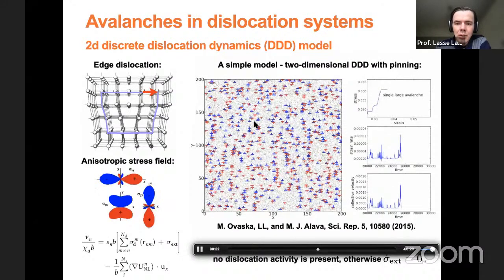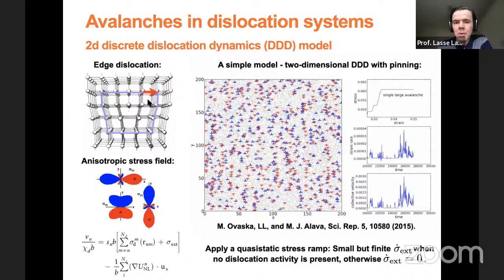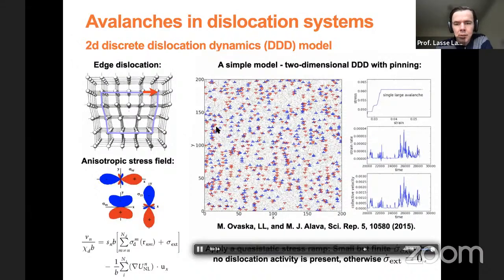So here you have these blue and red symbols, which are dislocations of two different signs. So they have a topological charge associated with them, which is called the Burgers vector. And so in this simple geometry where the dislocations are only allowed to move in the horizontal direction, you have two different signs of the dislocation. These are edge dislocations, so on the atomic scale, they would look like this, but here they are just point particles in some continuous elastic medium.